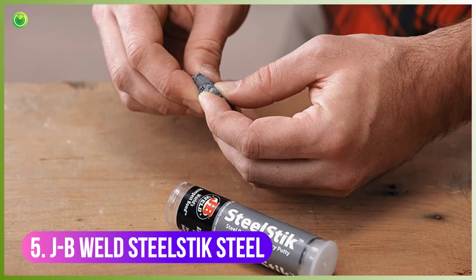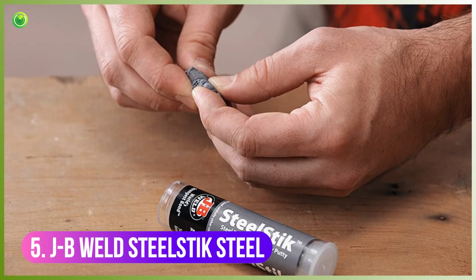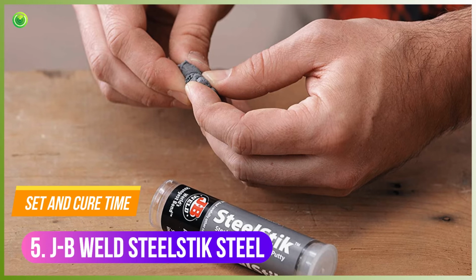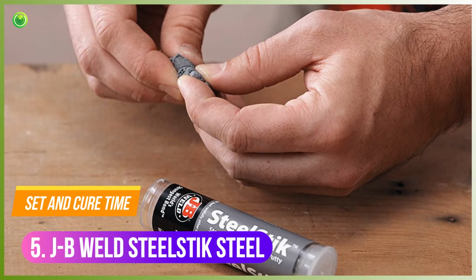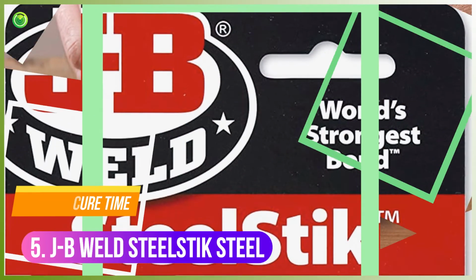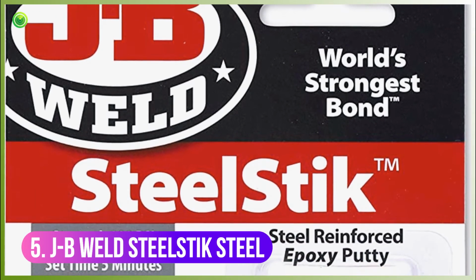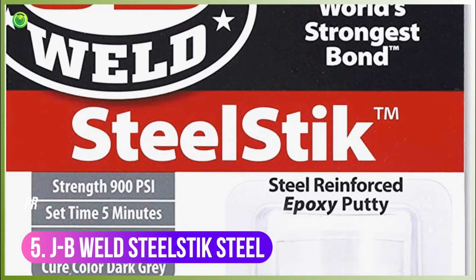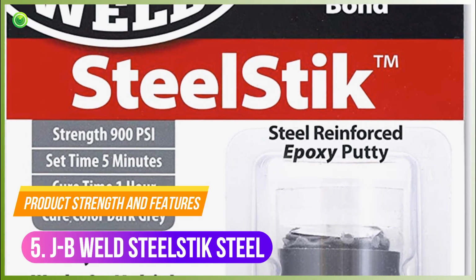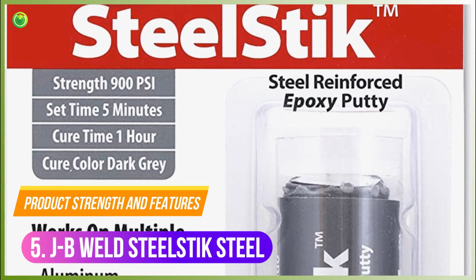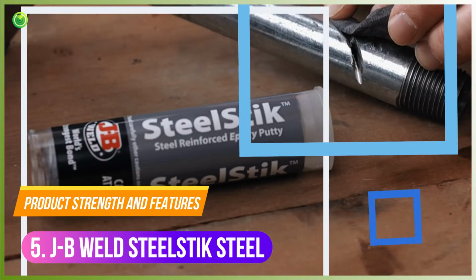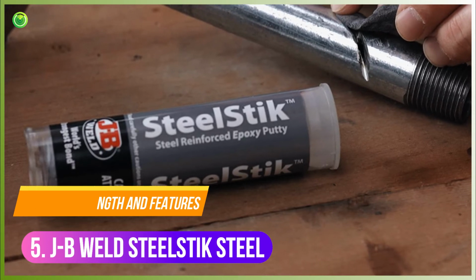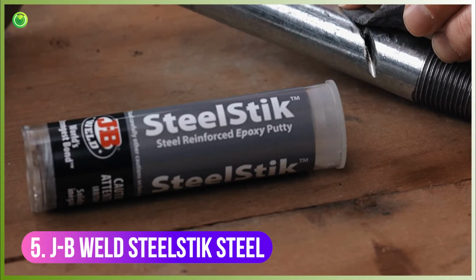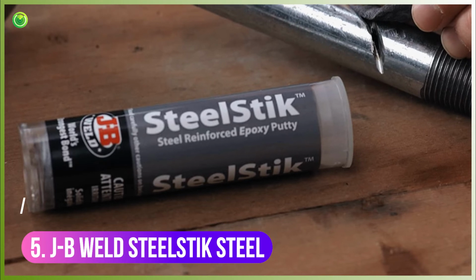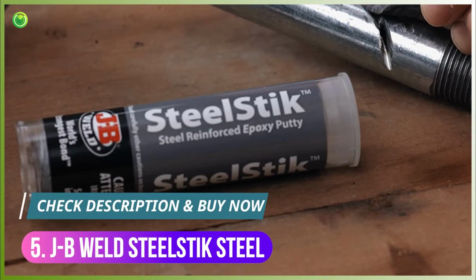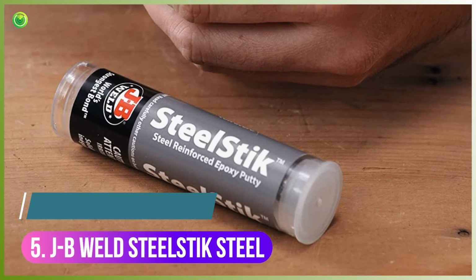It's also safe when in contact with potable water. Set and cure time. After you knead the two-part formula using your hand, the product cures in 1 hour and is set in 5 minutes. Its cure color is dark gray. Product strength and features. The product possesses a shear strength of 900 psi. It can withstand temperatures of 176 degrees Celsius, 350 F. It can also withstand intermittent temperatures of 232 degrees Celsius, 450 F.